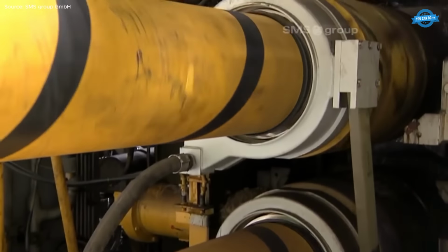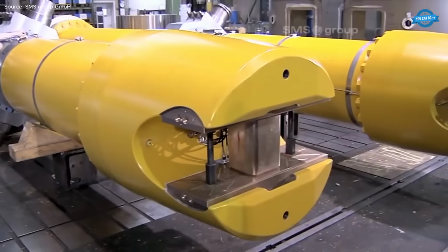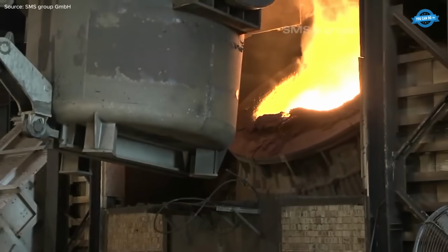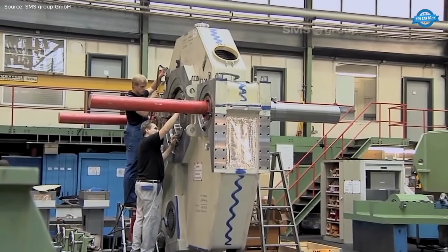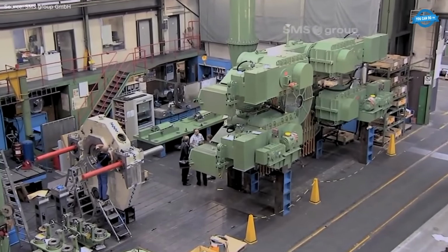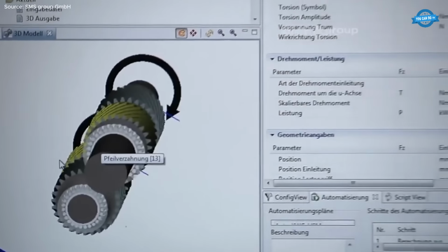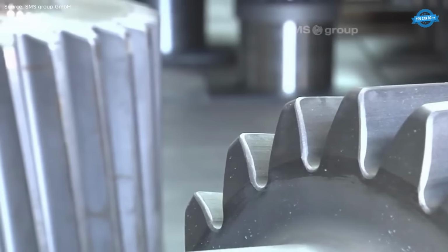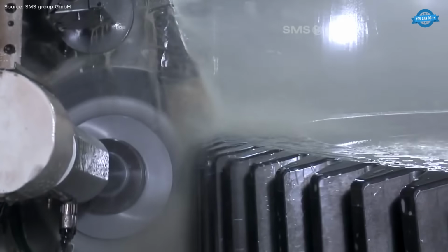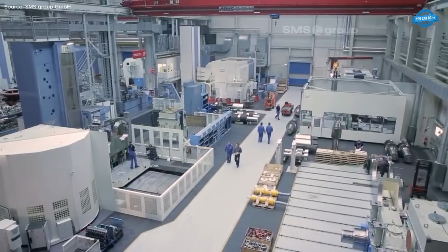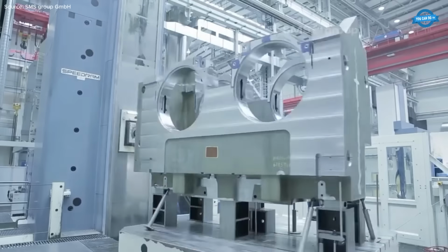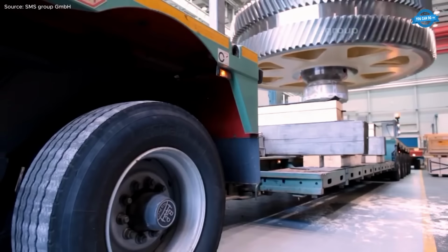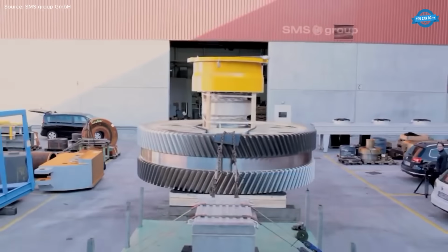Production of a large gear wheel begins in the welding shop. Fully mechanized submerged arc welding is applied to all joints to ensure deep penetration and consistent weld quality. After welding, the gear blank undergoes stress relief heat treatment to eliminate residual stresses and stabilize the structure before machining. Advanced milling and turning centers then machine the blank under strict dimensional supervision.